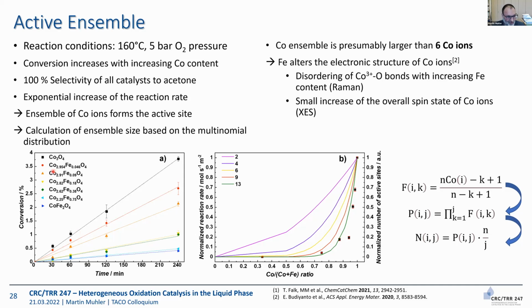systematic trends. Cobalt 3 O 4 is again the best catalyst, as in the gas phase. The straight line, the reason for that is because conversion is still very low. At high conversion, it would bend over. Yeah, and when we add now just a little bit of iron, conversion is less and less and less. We can plot that now in a different way, normalized reaction rate versus the cobalt to cobalt plus iron ratio. And then you see as soon as we add just a little bit of iron, the rate drops and even more,